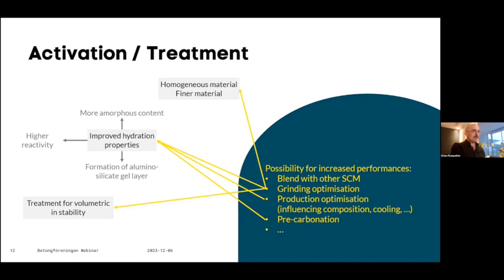which is also something that we want to have. Precarbonation would help again for the hydration because it can lead to the formation of an alumino-silicate gel layer at the surface of the particle. That's something you would like to do, and it's very good also in the way of CCU and CCS. Precarbonation can also help for the expansion problem by turning this free lime into calcium carbonate. So those are a few examples that we are working on. Sadly, I cannot share data on those, but those are the leads that we are working on.